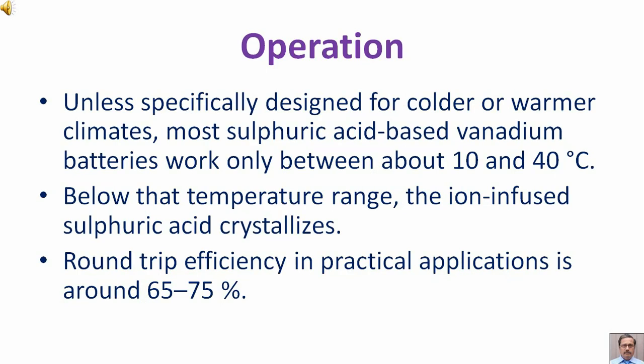Unless specifically designed for colder or warmer climates, most sulfuric acid based vanadium batteries work only between about 10 degrees and 40 degrees centigrade. Below that temperature range, the ion infused sulfuric acid crystallizes. Round trip efficiency in practical applications is around 65 to 75%.